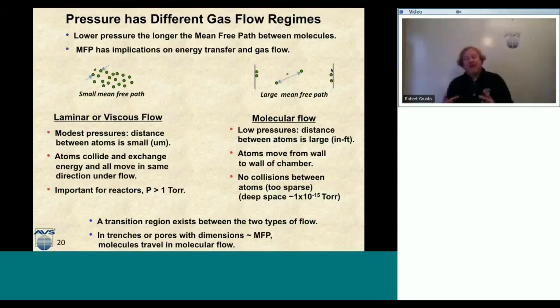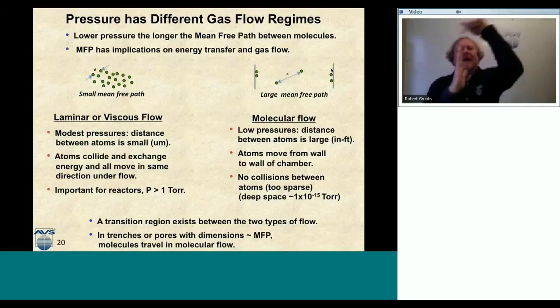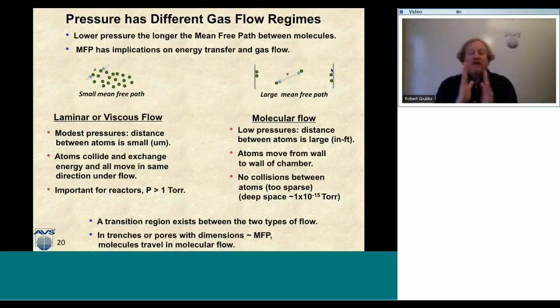One more thing I want to mention about mean free path is that I have a certain gas that has a mean free path on the order of microns, we'll say, but then I'm trying to coat this trench. And this trench is 200 angstroms, about 20 nanometers, in diameter, which is much smaller than the mean free path of the gases above. So when molecules are trying to coat a trench in ALD, I'm going to be undergoing a molecular flow type condition inside this trench, when the trench diameter is smaller than the mean free path of my ALD gas above that. So that's going to be important.